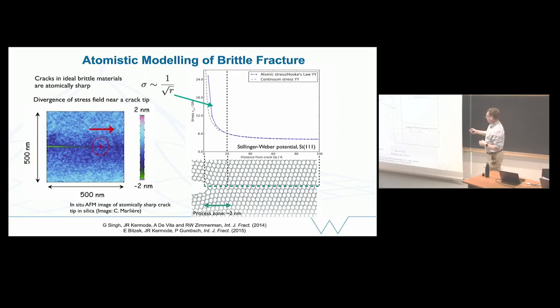So we know from continuum mechanics that as you go close to a crack, it's a mathematical singularity, so we have a divergence of the stress. The stress shoots up super fast. The real material is discrete. It can't go to infinity. It has discrete atomic sites, and so it goes up at a slightly different rate, a little bit softer, and actually the stress concentration is captured really well. So this is an example of somewhere where maybe you don't really need a complicated atomistic model.